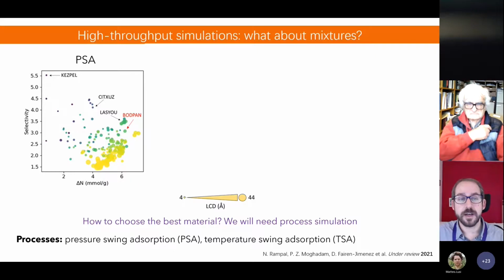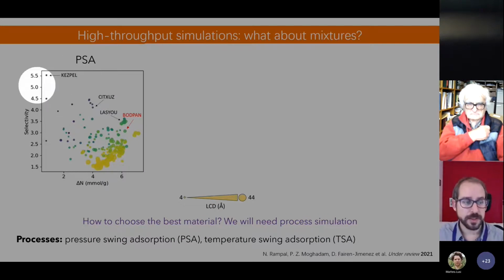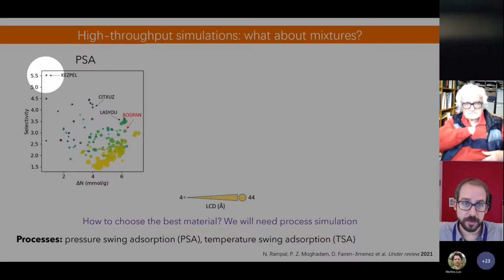This is the data that we can collect for a specific family of materials. In this case, we were taking copper paddle wheel clusters. Typical material is HKUST-1, but all the sister structures to this HKUST-1 material. This is for the PSA process, and you can see here the selectivity of CO versus nitrogen versus the working capacity. We want to have materials in this corner, materials with high working capacity. We absorb a lot of CO, we remove a lot of CO, but also very selective. We only want to do this with CO, not with nitrogen. And as you can imagine, this is very challenging, it's very difficult or almost impossible. If a material has very high selectivity, like this material here, it means that it's going to be very hungry for these CO molecules, and therefore it's going to be very difficult to remove them from the structure, and therefore the working capacity is going to be very low.